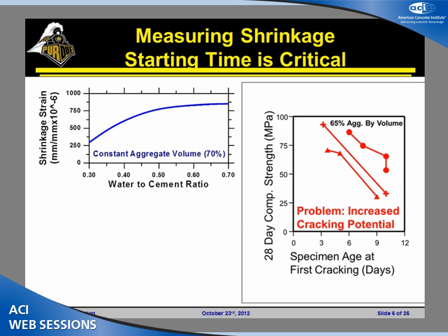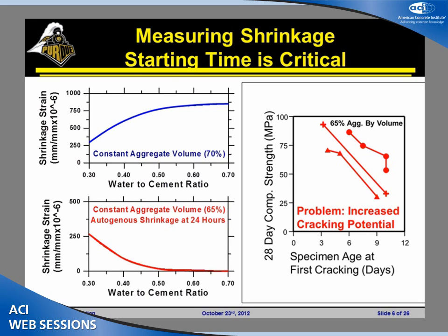One thing that's very important when we go back and we start to pull some of this data out of older literature, this is done with the ASTM C157 test. This is done with the free shrinkage test that starts at 24 hours. And what I really want to drive home here is when we're talking about high-performance concretes, just because you took 24 hours between placing the concrete in the forms and coming back to start the measurement, doesn't mean that the concrete also took that time off. So if you measure the autogenous shrinkage that's occurring during that time, what you can see is this is the amount of shrinkage that's being missed out on, all right, while the concrete is in those forms.